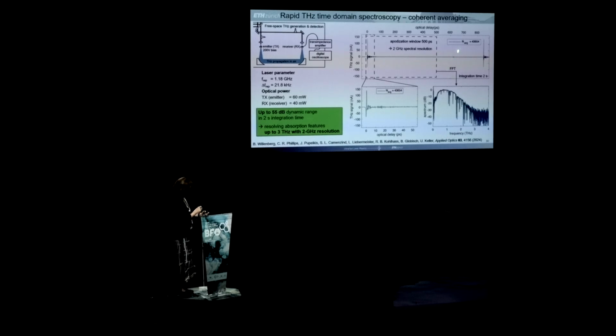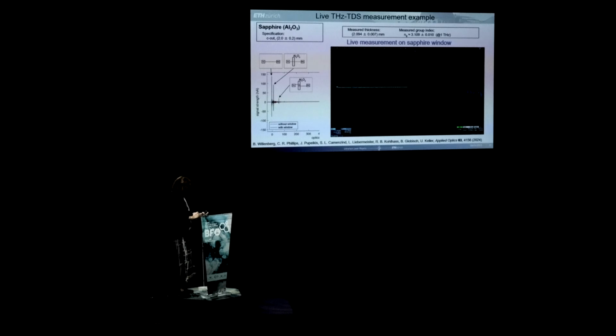You see here that we have a little bit of a spurious signal. This is not something unexplained, because it just shows you that the terahertz signal gets reflected and comes back and gives you another nice interferogram. So this shows you an actual measurement, again a pump probe experiment, but now on the scope, because the measurement takes not much time. Then we put, for example, a sapphire window into the beam, and you see how it changes. So this is how fast you get ultra-fast measurements done.